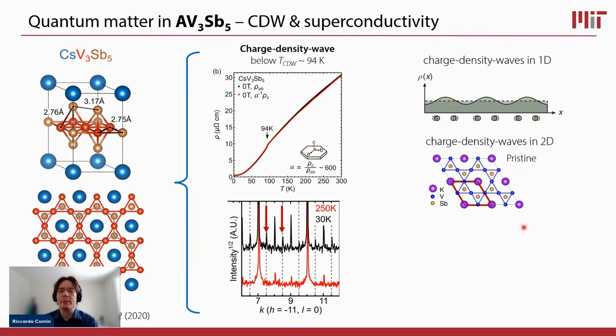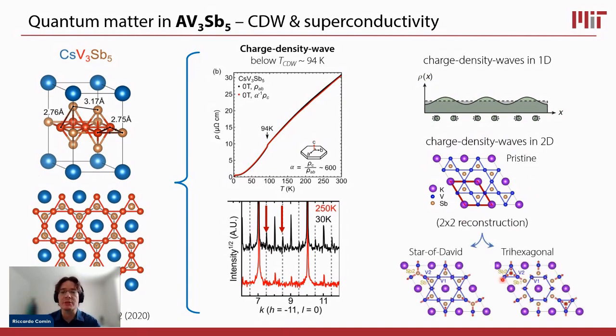And if we look at the Kagome structure, this is the pristine unit cell of the Kagome layer. It's this small rhombohedron you see over here. And this is the undistorted Kagome lattice. But if we create a charge density wave on a Kagome lattice, there's two different types of charge density waves that can appear, or two different patterns of reconstruction. One is called the Star of David, where essentially the bonds that are drawn in blue here, they shrink, they become smaller. So all these triangles here on the Star of David pattern, they become smaller. And the other one is so-called the trihexagonal, where you have that the unit cell essentially breaks into hexagons that become smaller in size, so they collapse a little bit, and triangles on the two sides that also collapse a little bit.